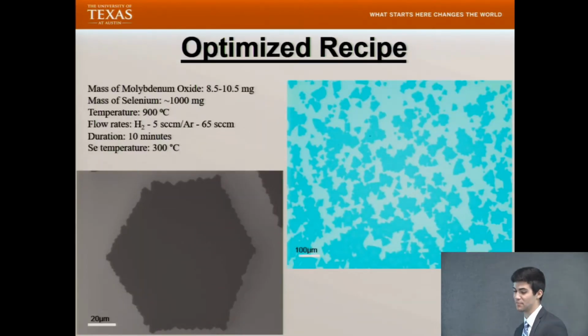So here's my optimized recipe and some images of the successful growths that I've achieved by using this recipe. This here is an optical image, much like the one I showed earlier, and this is a scanning electron microscopy image. And really, both of these images just illustrate large, uniform MoSe2 monolayers.